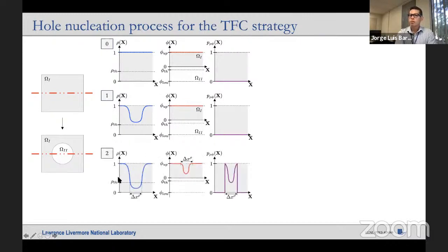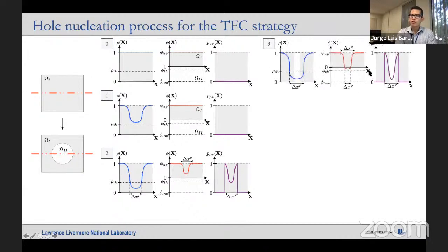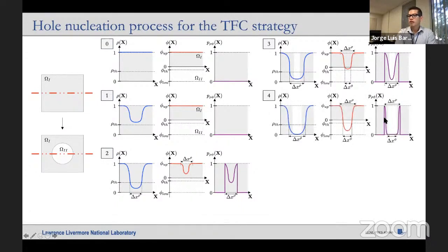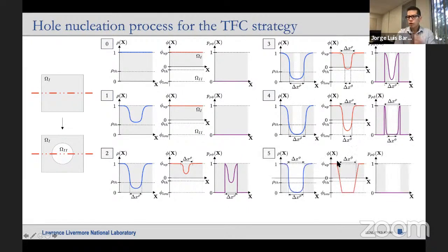But at some point it will go beyond the threshold, and in this region where it's beyond the threshold, the penalty is active. Because of the influence of the penalty, the level set field starts going down, dipping, as you see here. This process continues until you cross the zero isocontour. When this happens, the hole is generated. And throughout the process, this hole is getting bigger in size. At the end of the whole hole seeding process, you have a regularized level set field, the penalty is off, and that's because of the influence of the density field. This is the entire process for when you generate a hole.